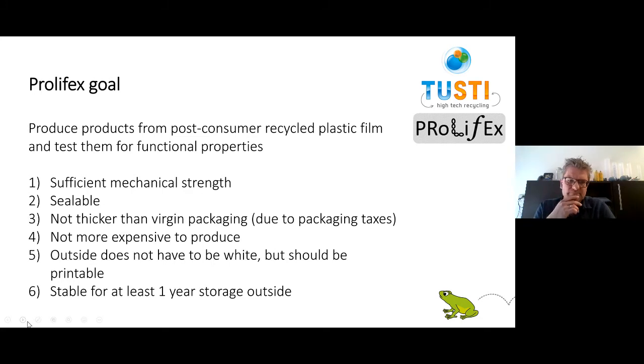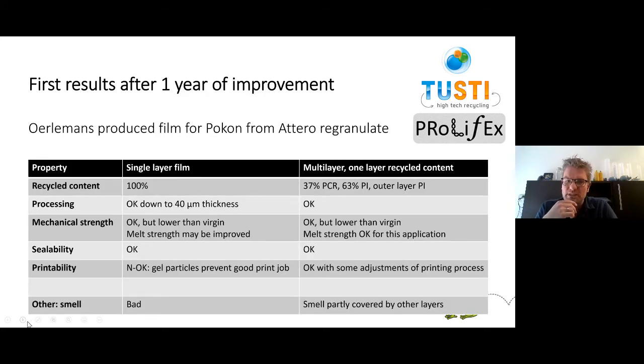If we go to the next slide, I can show you some results that we have obtained. So we made a first film from Attero regranulate, made it into a single layer and a multi-layer material, and looked at what the quality is now. Do we achieve what we want? So this is more or less a base case after the first years of experiments. And what you see is that the single layer film can be made from 100% of recycled content. That does give an acceptable production speed at Oerlemans, even down to 40 micrometers thickness. The mechanical strength of that film is okay, but it's a bit lower than virgin. So we need a bit of improvement there.